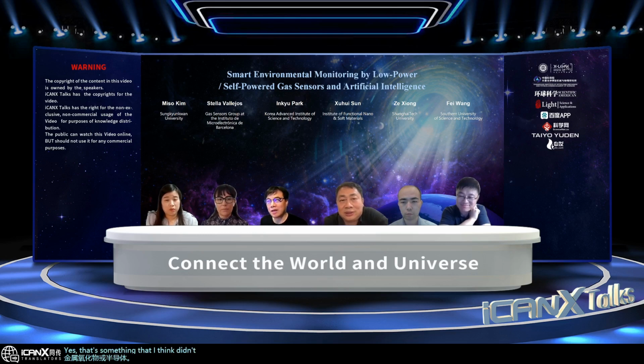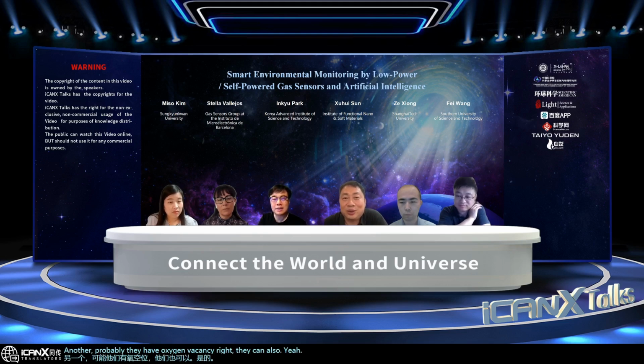Yes, that's something I didn't think very carefully about before. But as far as I know, one approach could be to generate some hydroxyl groups at the surface by surface treatment like oxygen plasma treatment, etc. Then those hydroxyl groups can capture the reducing gases. Instead of having oxygen ions, we can use the hydroxyl groups to react with the reducing gases, probably. Yeah, I know, because probably they have oxygen vacancies, right? They can also keep working on that. Actually, it's a very interesting topic. People ask me how to work in a non-oxygen environment.